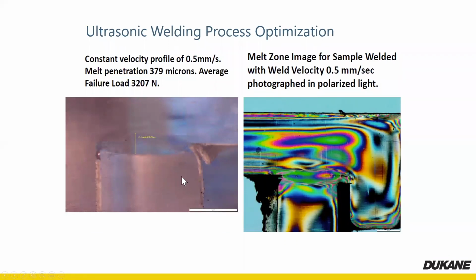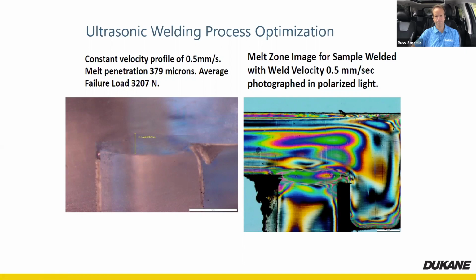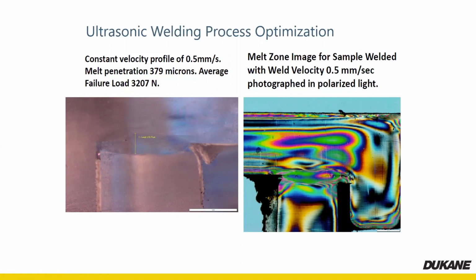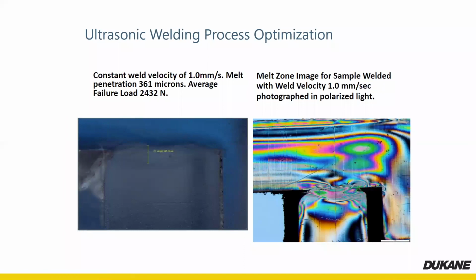What's important to note here, though, is you can't really adjust this velocity on a pneumatic welder. You can adjust your flow control and you can adjust your pressure, but the plastic is ultimately going to determine how fast you can go. You can apply so much pressure that you're going much faster, but you're not impacting this heat affected zone as well and as consistently. You're just kind of plowing through the plastic and generally just cold forming it. With the servo, because I can very accurately and consistently adjust that velocity, I'm actually having a direct impact on the heat zone. So again, this is a polarized image, and you can see that the heat zone on the right there has gotten much deeper into the plastic than the one previous.